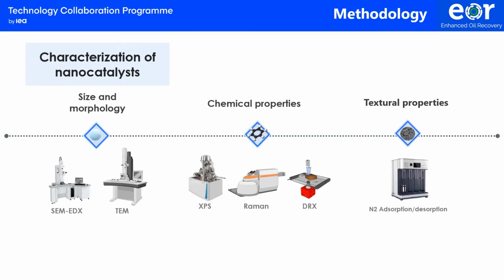As for the characterization of the nanoparticles, the size and morphology were validated through scanning electron microscopy and transmission electron microscopy. The chemical properties were measured by X-ray photoelectron spectroscopy, Raman spectroscopy, and X-ray diffraction. Finally, the surface area was measured by nitrogen adsorption-desorption.